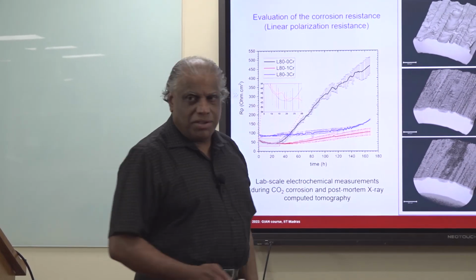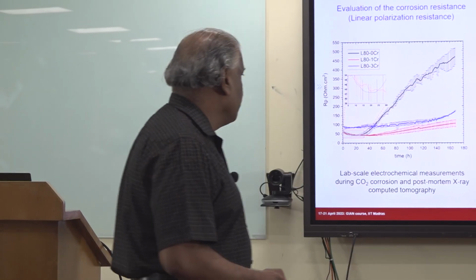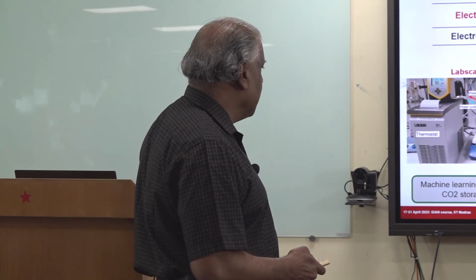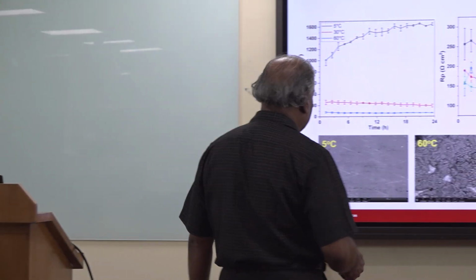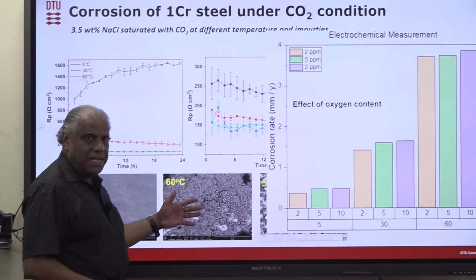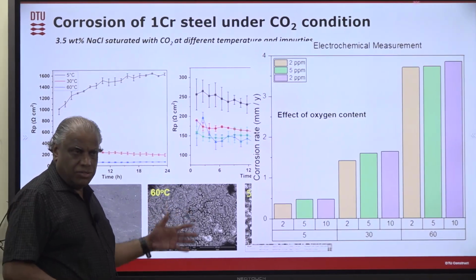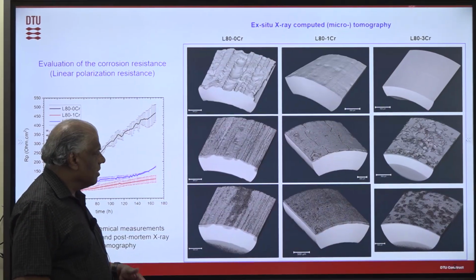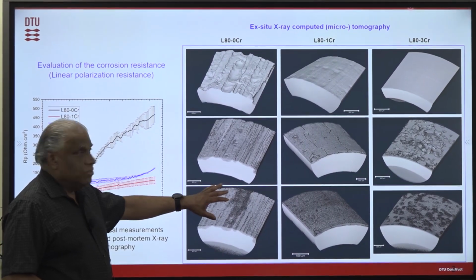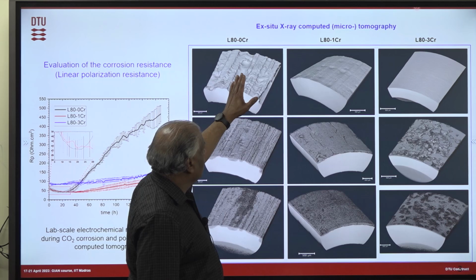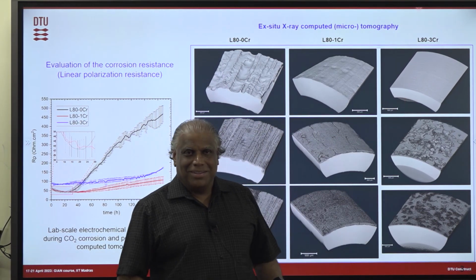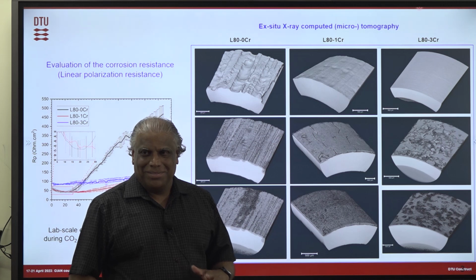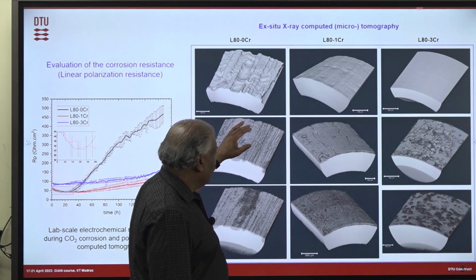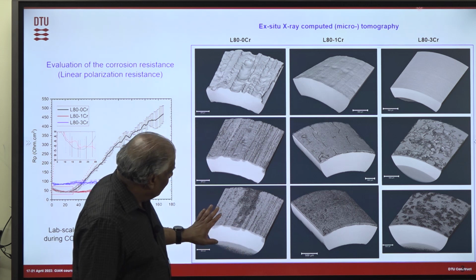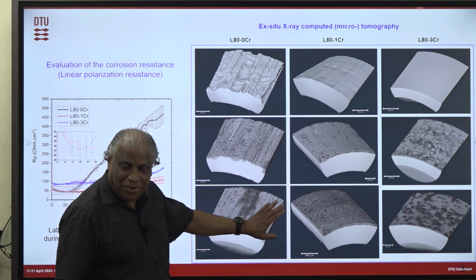In this work, we also use a lot of X-ray tomography and synchrotron, because we want to understand what scale is forming here and how the scale is building up with time. So we use tomography so that we can get this 3D image. Here you can see the difference between 0 chromium, 1 chromium, 3 chromium. Clearly you can see why they add chromium into the material. In this particular case, there was this scale, right? Corrosion product. This is a 3D X-ray image.